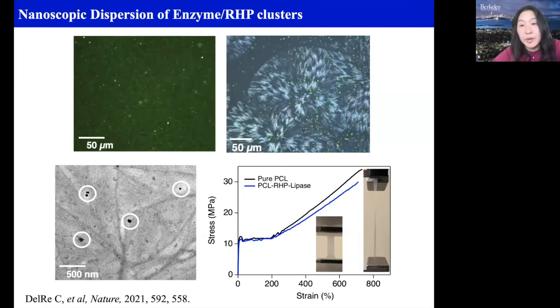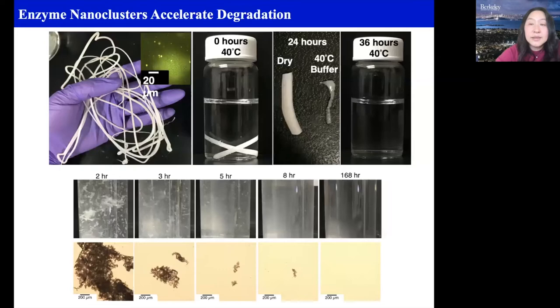And from the engineering point of view, adding the enzyme really cannot compromise the host polymer properties, and in this case we particularly focus on the mechanical properties. That appears to be the case because we only add a very small amount. In this case, the enzyme is only about 2% by weight, which is almost the same as what you tend to have for other additives or dyes. We can add it just as an ingredient, like you add color pigment, when you go through the extrusion process. This basically shows that we can go through a single head extruder and get